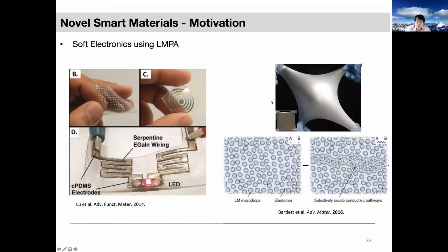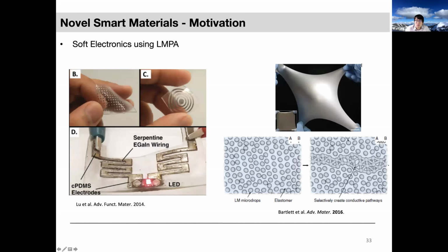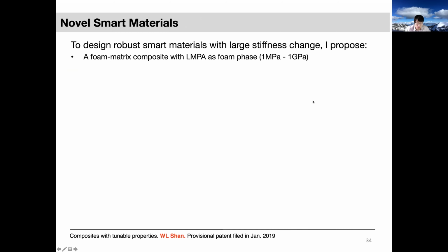More recently, the CMU group also did this. They mix LMPA particles or droplets into an elastomer matrix, and they're able to make this composite. This composite is not conductive right out of the manufacturing process, but they can use some sharp object to scratch the material.